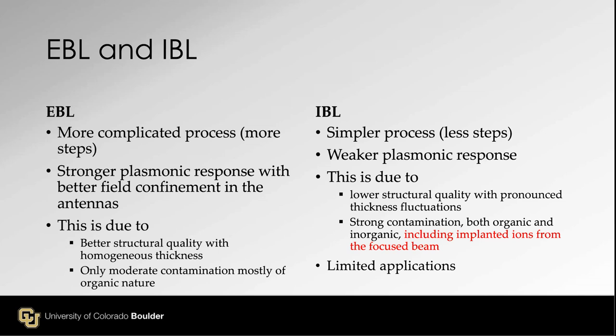Okay, so most of the time, resolution-wise, EBL and IBL is about the same, but nano device fabrication using ion beam has limited applications because of the implantation contamination issue for gallium. So how about different ions? Yes, helium ion microscope. If you use the helium beam, helium is a gas, so it's less implantation issue.